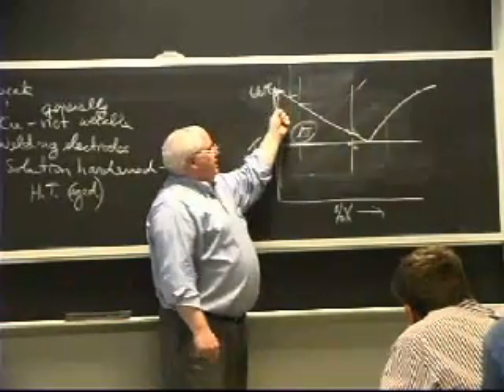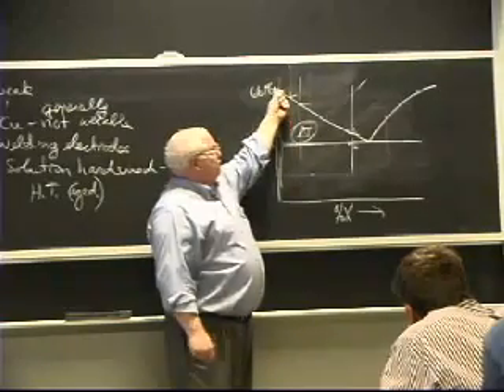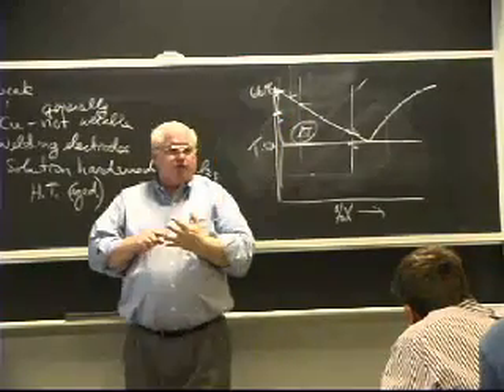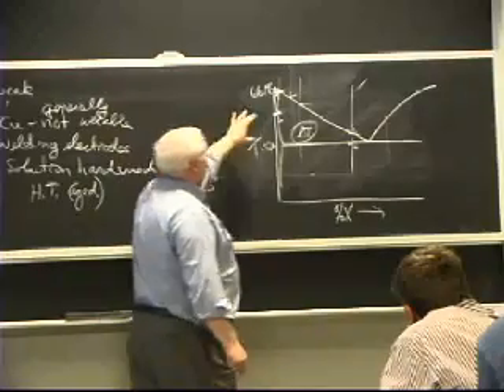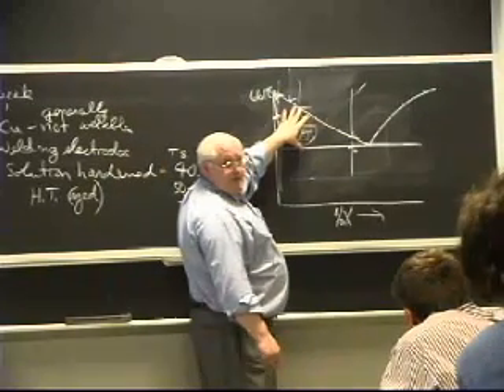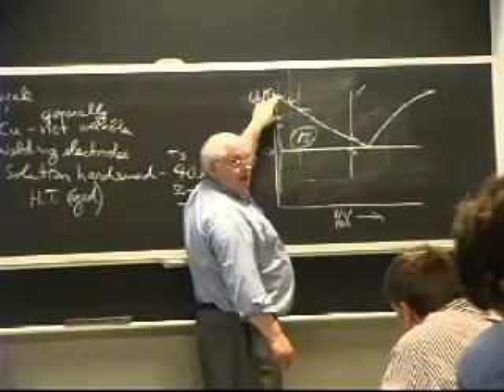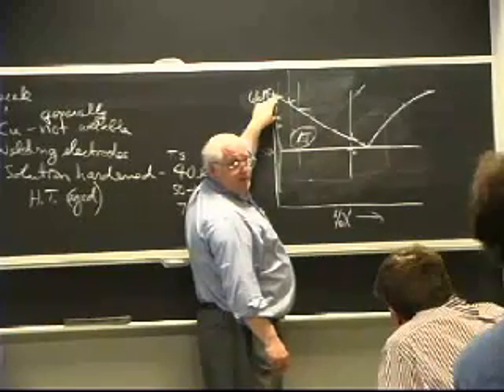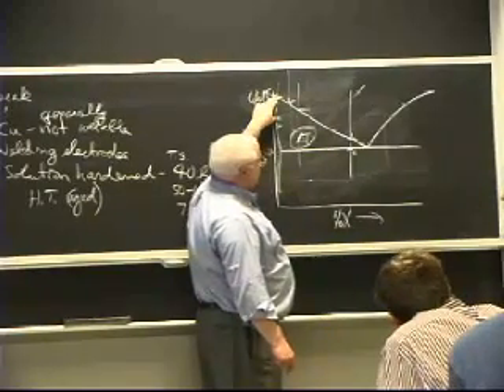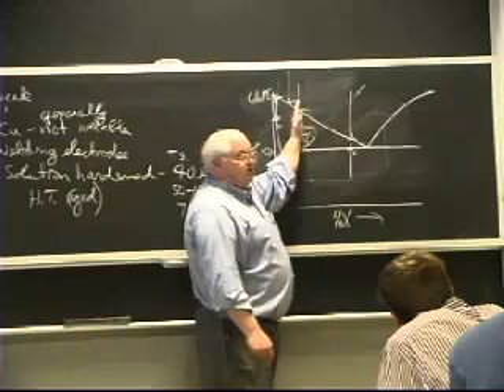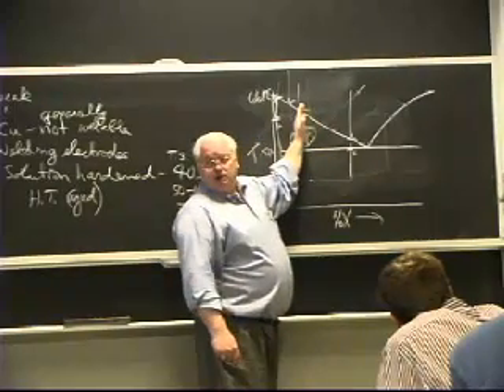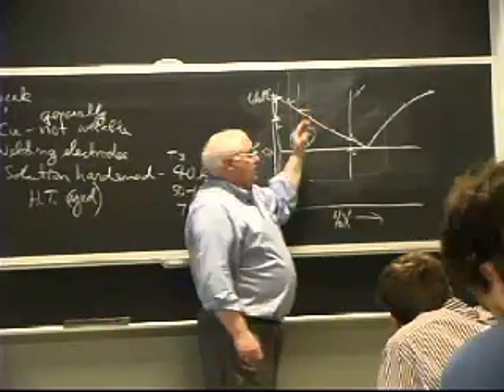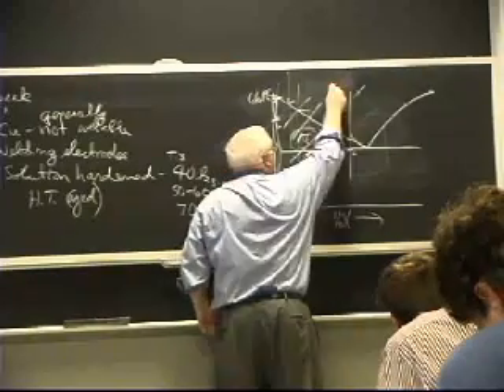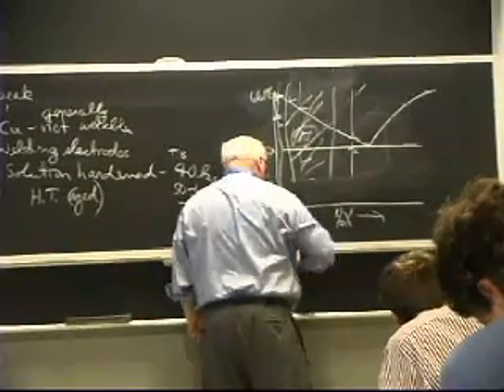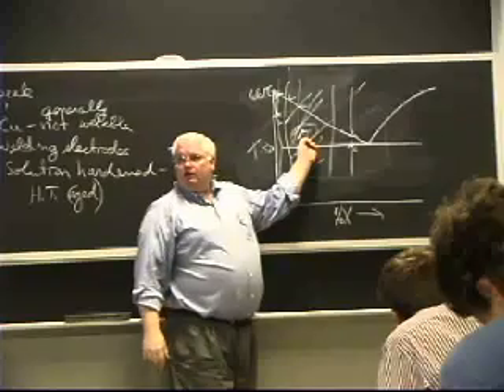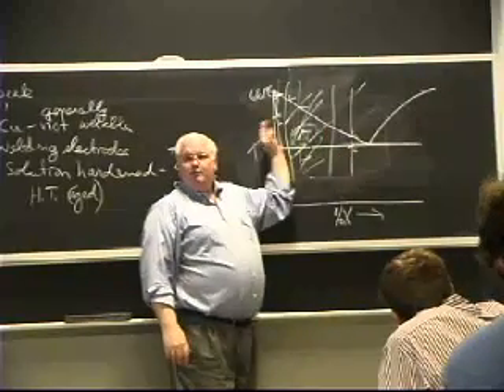I have some other alloys, some 1000 series welding electrodes that are nearly pure, and I could weld the 1000 series or the 3000 series with those and have a small delta T. But if I take a lightly alloyed base plate, like a 3000 series, and try to weld it with a 4000 series, I'm going to end up with a weld metal that's halfway in between. It's going to crack, right? So you want to avoid this region in here. Don't weld with a composition that ends up in between with big delta T's. Be over near here or be over near here.